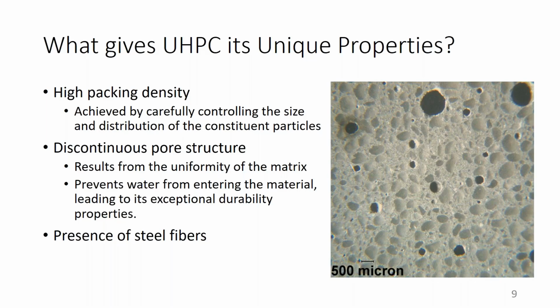Another reason why it's so successful is because of this discontinuous pore structure. If you look at the slice on the right, and you can see the 500 micron range at the bottom there, you'll notice that the pores are not connected. The discontinuity of the pores is one of the reasons why the material is so impermeable to water. And if you kill the water cycle, you basically kill the freeze-thaw cycle and you get this exceptional durability.